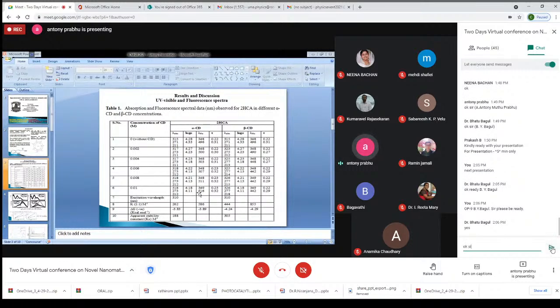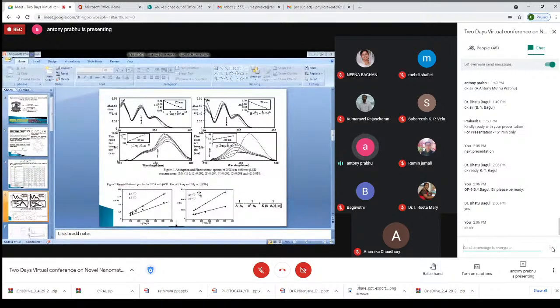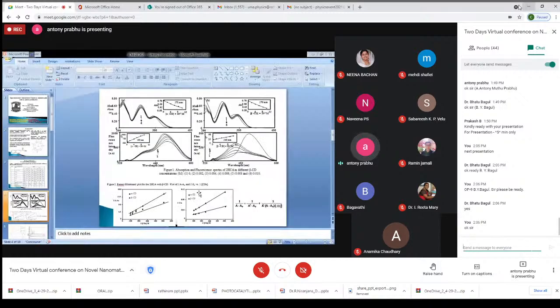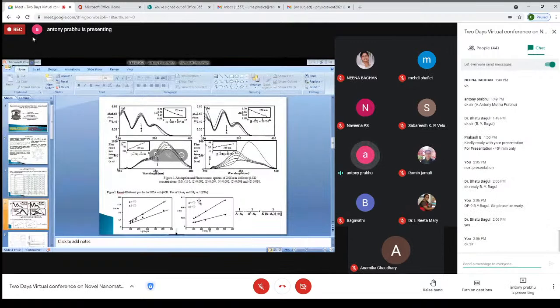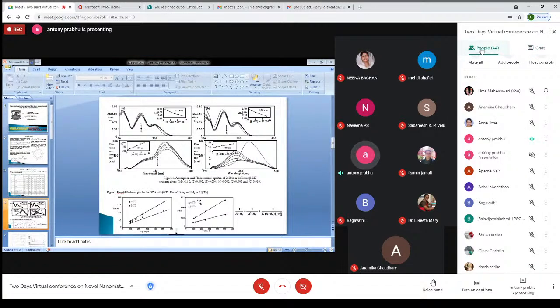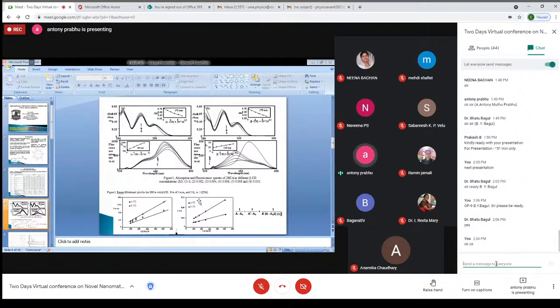This slide shows the absorption and fluorescence spectrum of these compounds with the encapsulation of hydroxycinnamic acid molecules. In this UV-visible spectrum, the absorbance decreased in alpha CD and beta CD, but the emission intensity gradually increased, and the emission maximum was blue shifted from 490 to 450 nanometers. So this result indicates that the 2-hydroxycinnamic acid molecule was encapsulated into the cyclodextrin cavity. Then the 2 graphs are 1 divided by concentration of CD versus 1 divided by A minus A0 for absorption data, and 1 divided by CD concentration versus 1 divided by I minus I0 for the fluorescence spectrum.